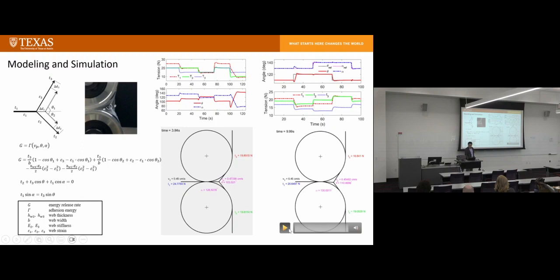So basically, initially we start from controlling the tension. We have three parts, right? We have the incoming web, the web going out with transferred graphene, and also the recycled copper. So there are three webs involved in it, with three tensions, T1, T2, T3. We can control the tension, and we can control the peeling angle, where the peeling angle is over here.